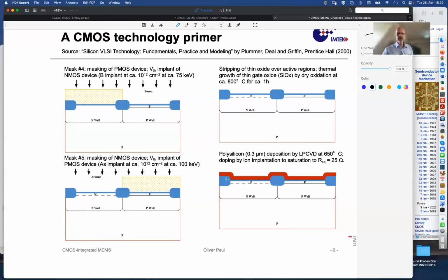And this gate material covers the whole wafer, of course, because the wafer is in the oven, the gas goes everywhere, and the wafer is again covered. So this was the first deposition step. So far we had growth steps. No, actually the silicon nitride of this low-cost process was also deposited.